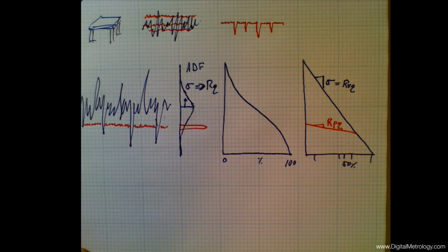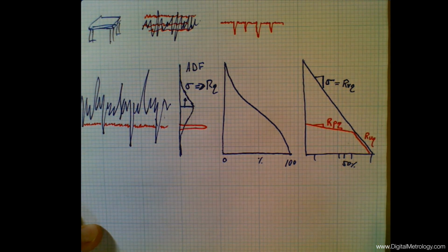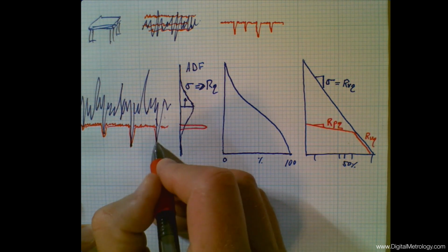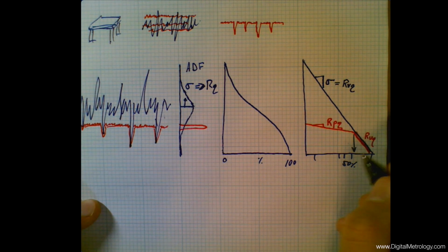Our Vq number is actually calculated off just this tail end of the curve, Rvq, and it predicts the original roughness of the blue surface back here. See, once we're done, we only have the plateaus and the valleys remaining, and we would have this red part of the curve over here to work with, but it's enough to predict what the valleys used to be, and it gives us this intersection point where plateaus meet valleys, and this is the Rmq number.